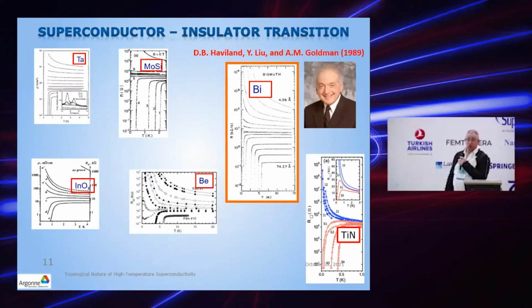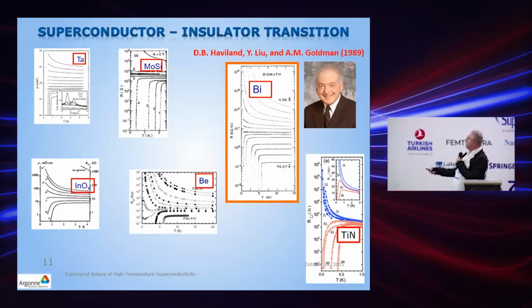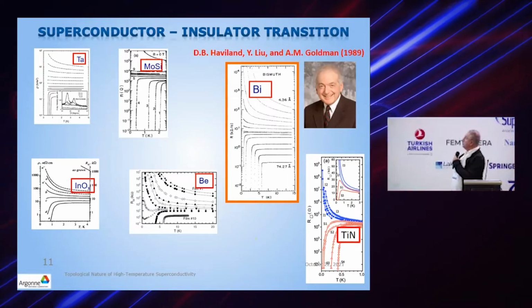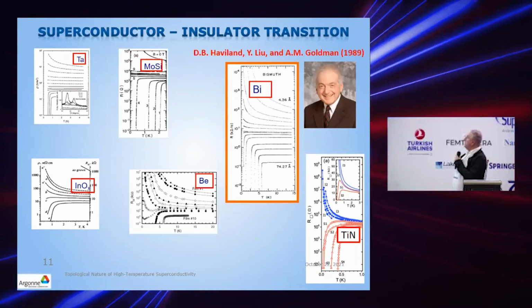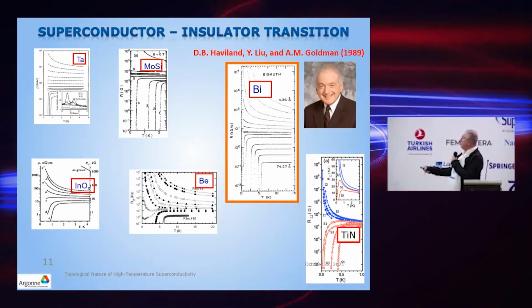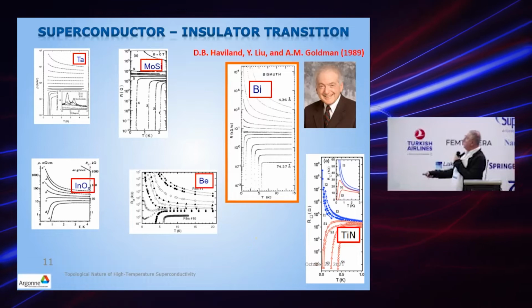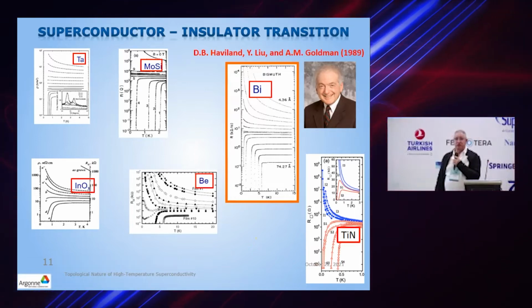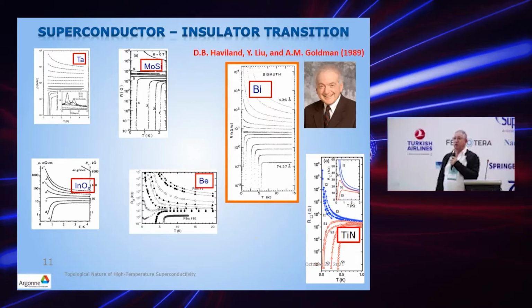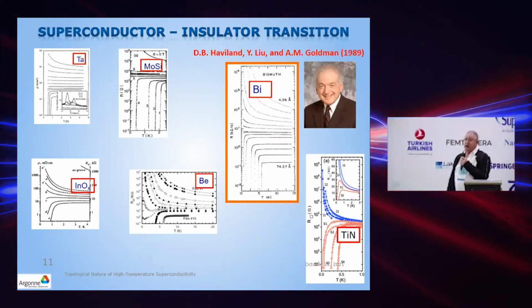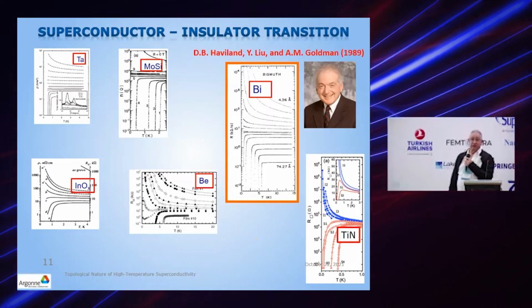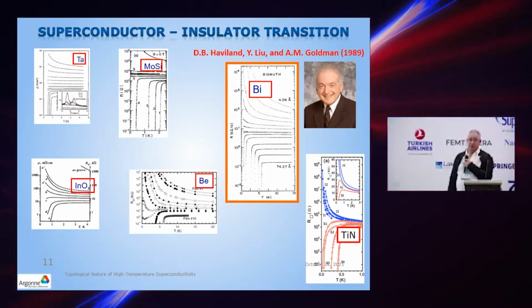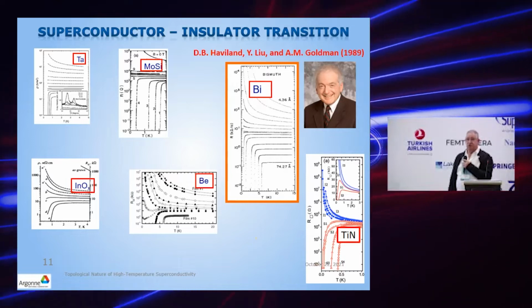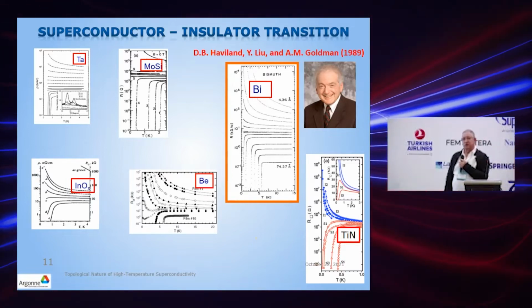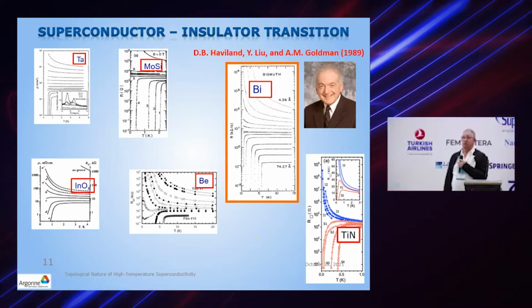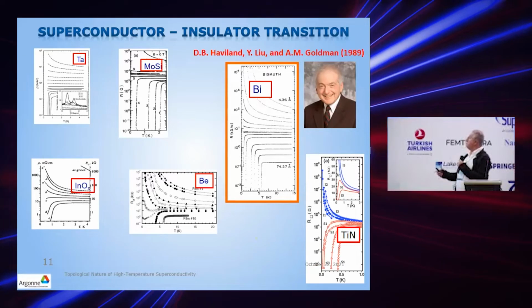So this is just the iconic data where the superconductor insulator transition was observed by Haviland, Liu and Goldman. This is indeed the iconic picture. There is data from other different materials. And now it's a little bit forgotten because this discovery was a little bit in the shadow of the development of high temperature superconductivity. But basically the existence of this superconductor insulator transition in two-dimensional systems contradicted what was believed to be true from our usual textbooks.